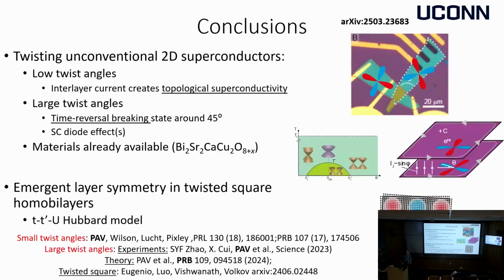So to conclude, I talked about the physics of twisted superconductors, taking superconducting materials in monolayer form and twisting them. If you take nodal superconductors with anisotropic order parameters, you can get a lot of new physics that can be introduced either by hand, like driving currents or magnetic fields, or by twisting to very large twist angles where you wouldn't expect anything interesting to happen in systems like graphene.